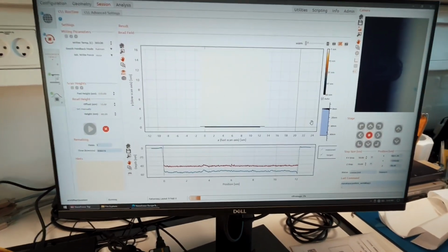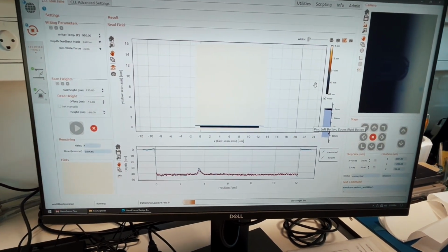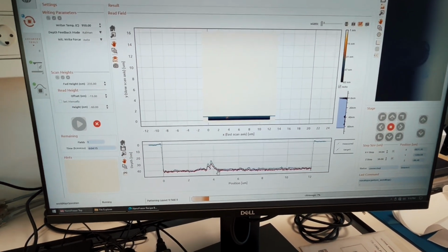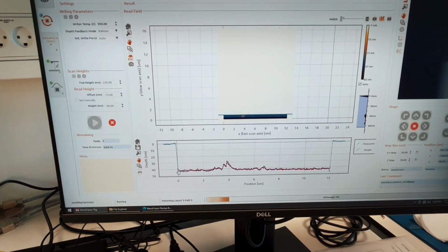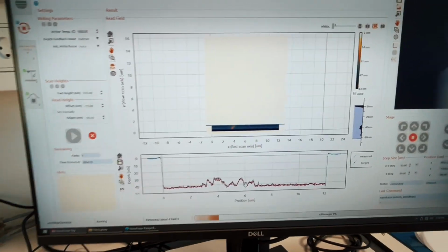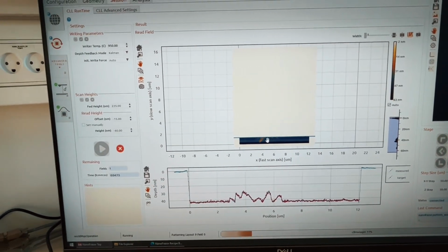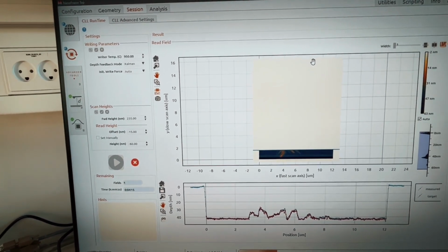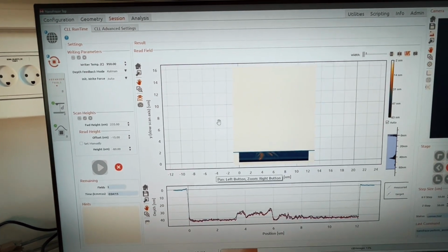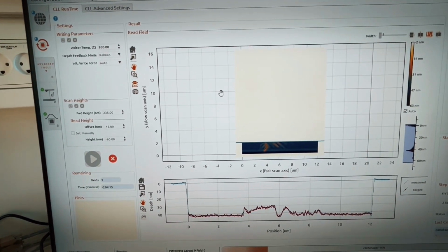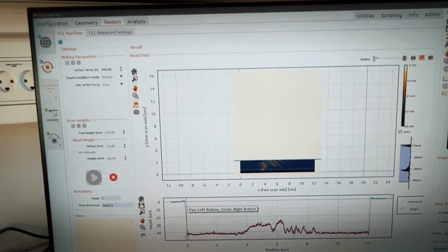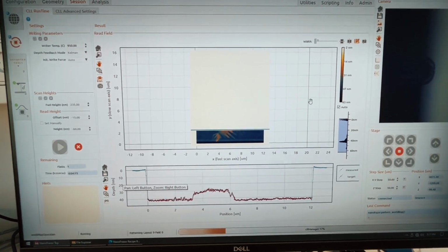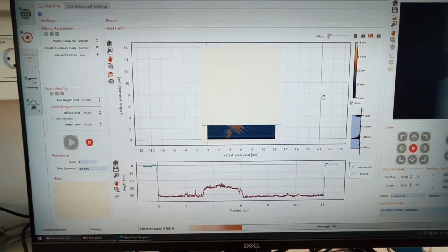I've done lithography for 30 years, and this is just like science fiction to me, although it's in our own lab. And you see now it's adjusting a bit. So the red line is the desired topography. It's writing Mona Lisa in a 12 by 16 micrometer area with a resolution of 10 nanometer pixel size or so, maybe 20. It has a depth of about 30-40 nanometers. Okay. Pinch me, I'm dreaming. Pretty close to molecularly precise.